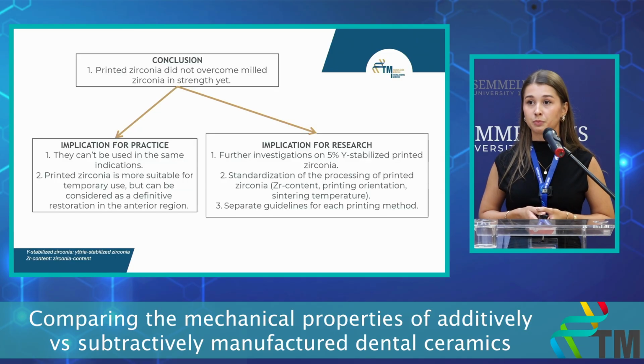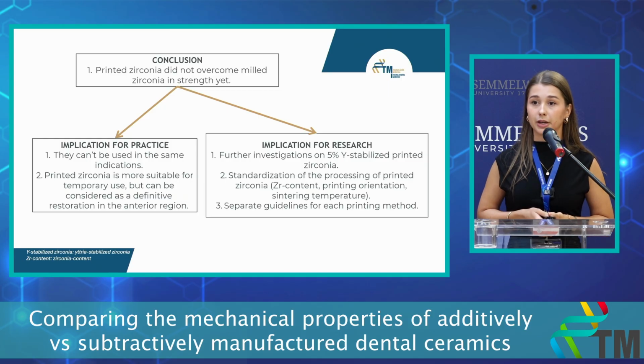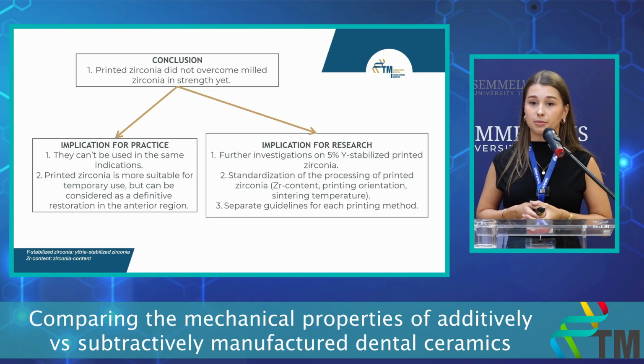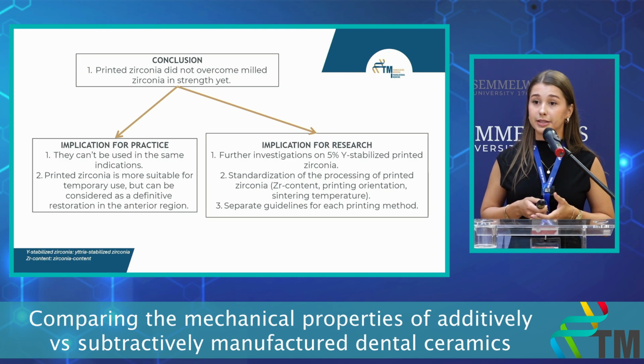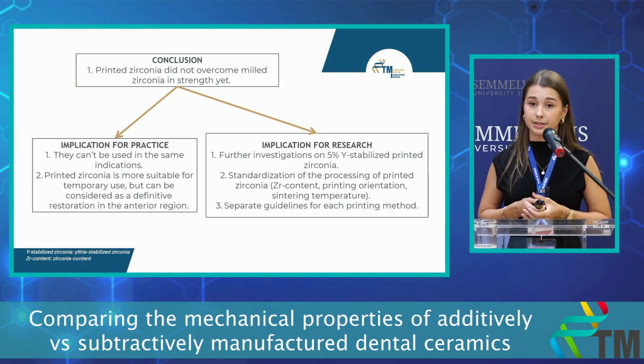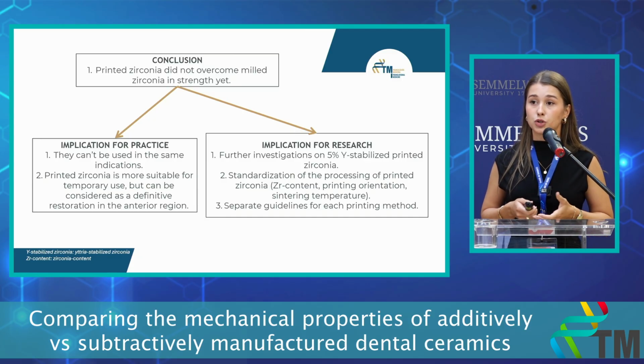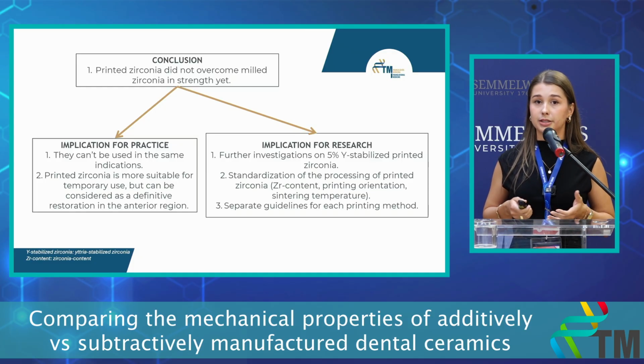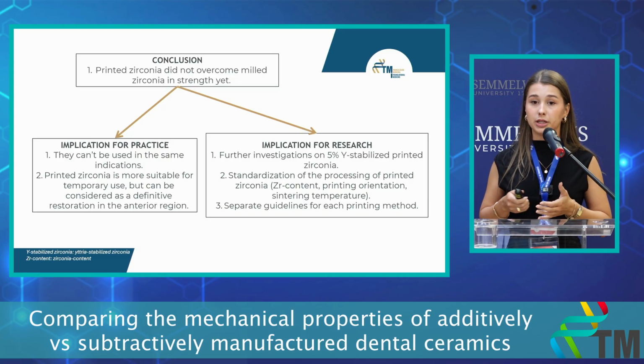But these articles use different brands of zirconia, different manufacturing techniques, and specimen dimensions, which leads to high heterogeneity within the studies. Overall, we can conclude that printed zirconia did not overcome milled zirconia yet, so they cannot be used in the same indications, and printed zirconia for now is more suitable for temporary restorations, but 5 mole percent yttria stabilized zirconia could give us really good results in the anterior region, so further investigation is needed on this material, and also we need standardization regarding the processing of printed zirconia, and we need separate guidelines for each printing method.